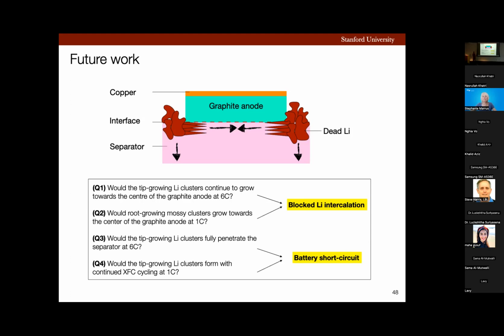In addition, at 1C, we observed mostly this crescent moon-like geometry of mossy lithium. I'm curious to know, would those clusters grow towards the center of the graphite anode and cover the entire circumference? Or would tip growing clusters also be observed at 6C if we continue cycling the battery? So these are the 4 potential questions that my work can lead to, and hopefully they can further shed light on the growth mechanism of lithium plating and how it causes battery failure.